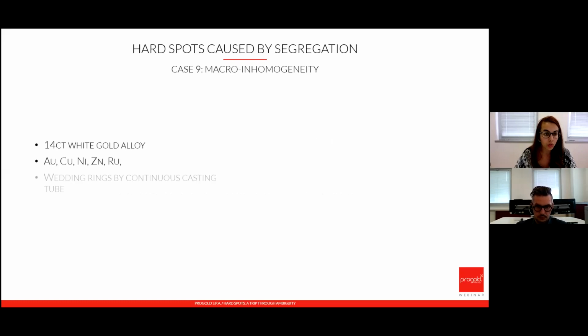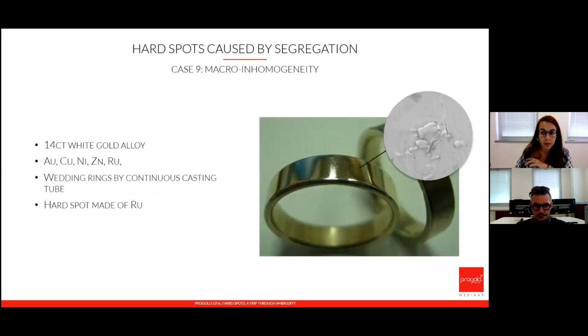Here I'm going to show you the first case, which is a very typical case in continuous casting. In this case, we're pulling the rod down and melting on top. It is a very slow process, and we're just pulling down the rod, and we have solidification rates that are different at every point of the process. I do want to remind you that the machine for continuous casting is not a machine made to melt.